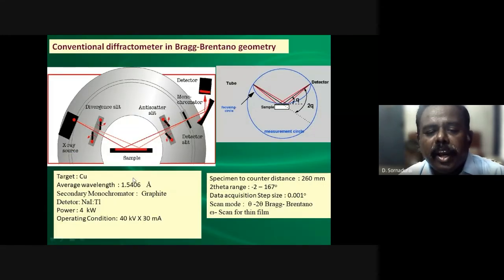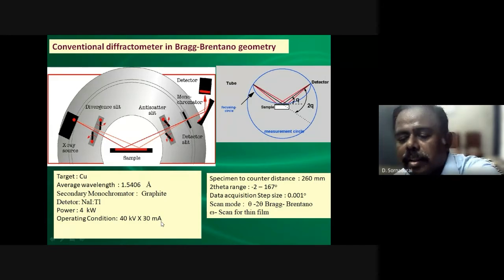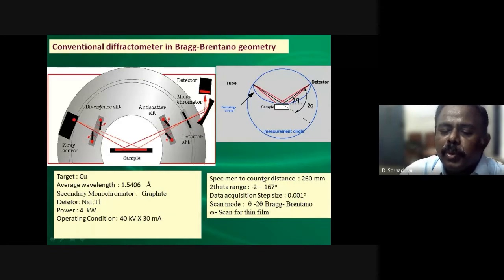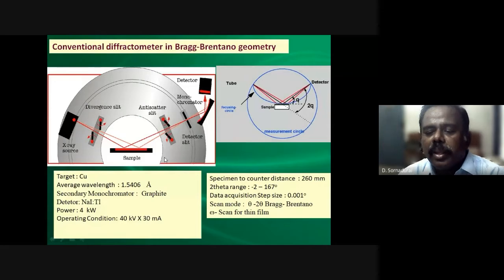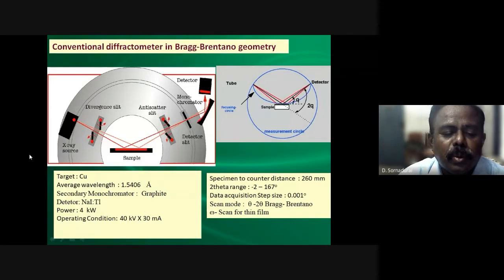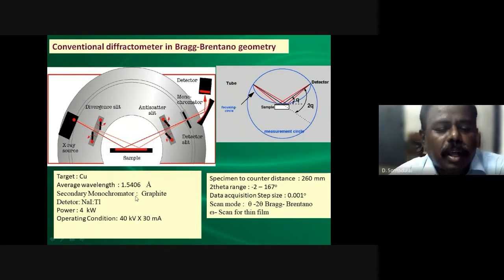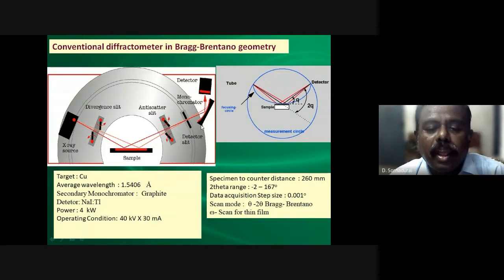This instrument, okay. So the entire circle is around 520 millimeter. Right here you can see the specimen to counter distance. This is the counter distance. This whole circle will be 520 millimeter diameter. The target here is copper K alpha, and the average wavelength of this copper K alpha is 1.5406 angstrom, and the secondary monochromator is graphite, and this detector is actually made up of